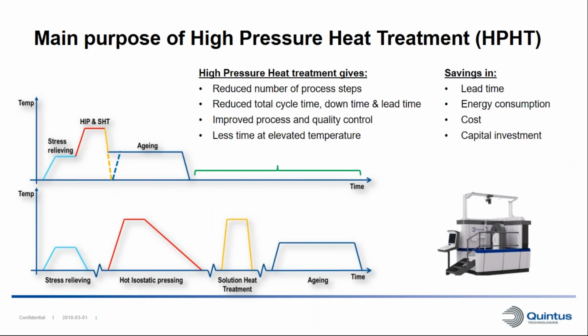And one of the main purposes with high pressure heat treatment is to be able to combine all of these steps into one cycle in the HIP. So if we see here, for example, we could in the HIP do the stress relief step, then we go up and we combine the HIP and solutionizing step. Then we cool fast in the HIP, either to room temperature and then go up to aging, or we actually stop the quenching at any temperature and we do a direct aging.